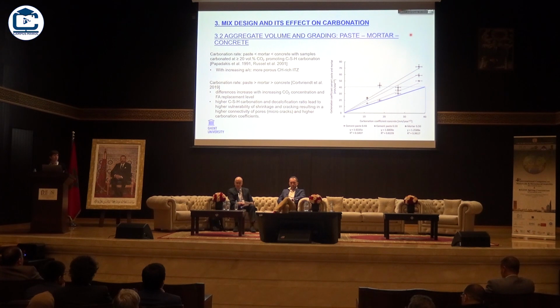And then actually you find contrary results in literature. There is quite some literature stating that carbonation rates increase with the addition of aggregates and coarse aggregates, which is then explained by the presence of the porous interfacial transition zone around the aggregates, making the transport processes go faster. On the other hand, there are also some papers saying, like in this graph, that if you relate the carbonation coefficient of concrete to the one of a mortar or a paste, it actually increases if you leave out the aggregates. Now, this could then maybe be explained by the fact that these mixes might be prone to carbonation shrinkage, leading to cracks, and in this way to enhanced transport properties.